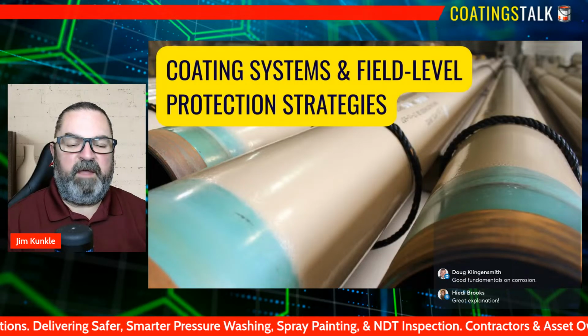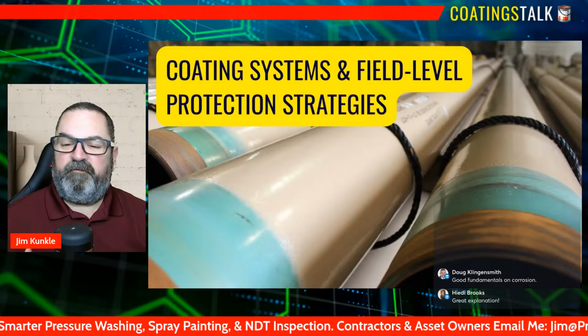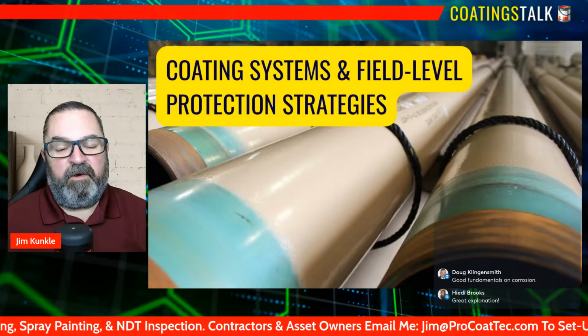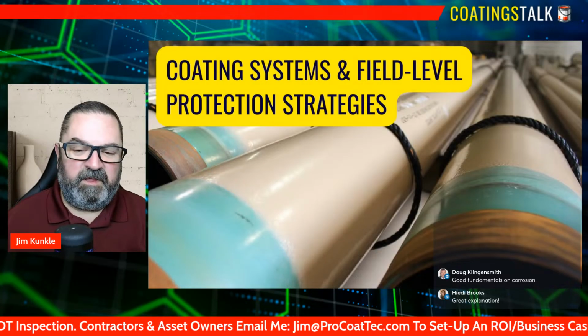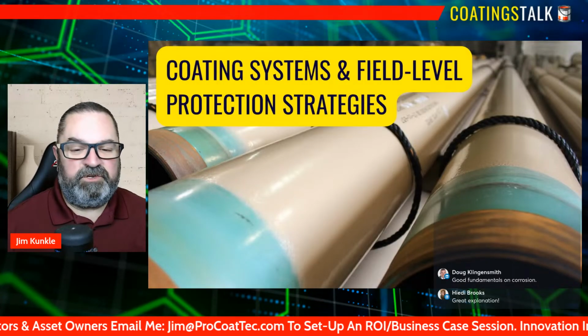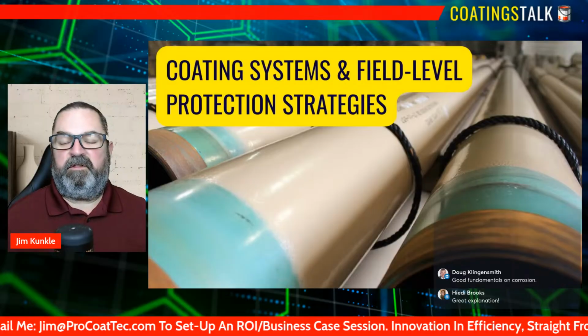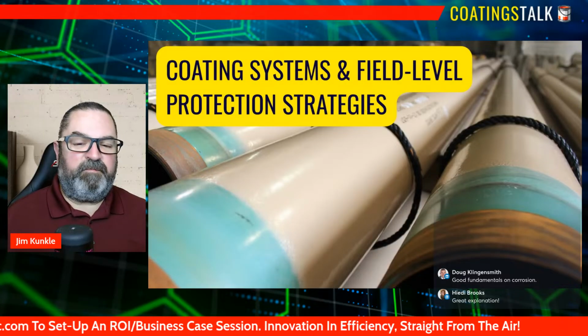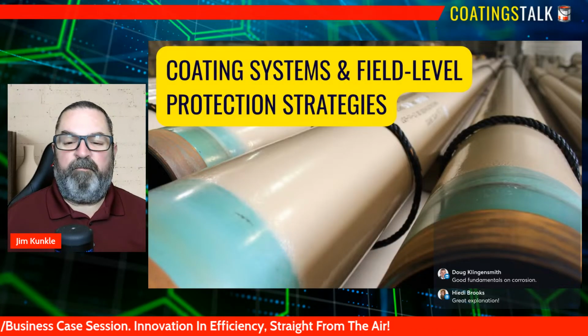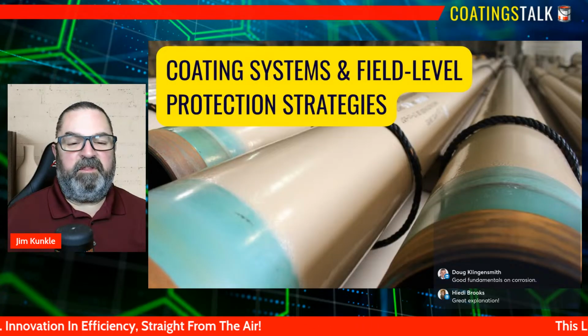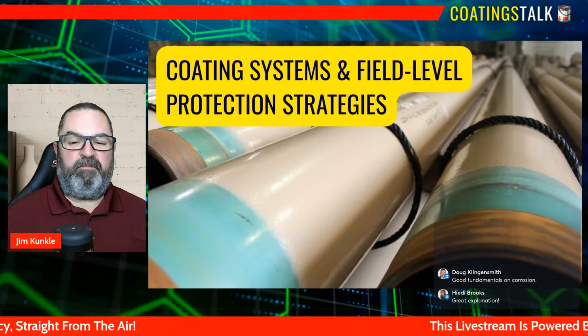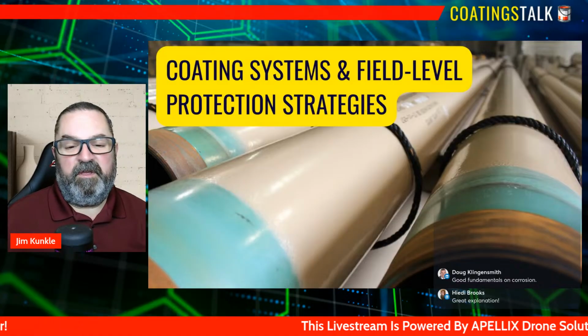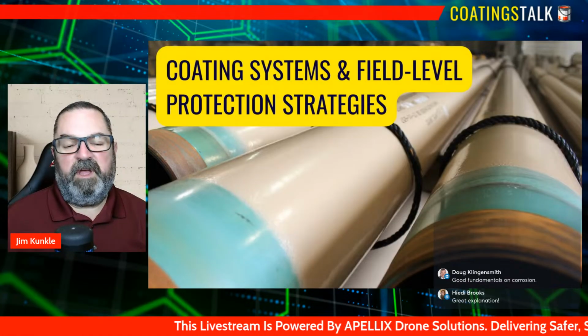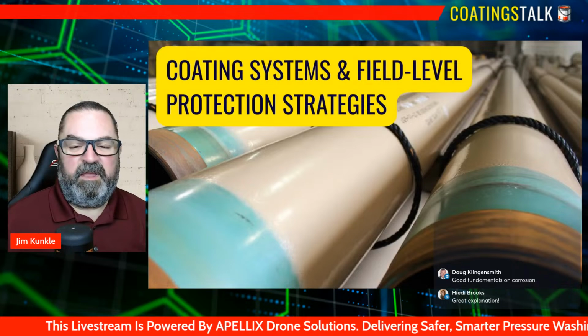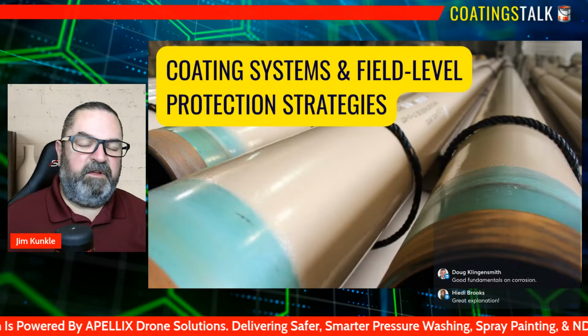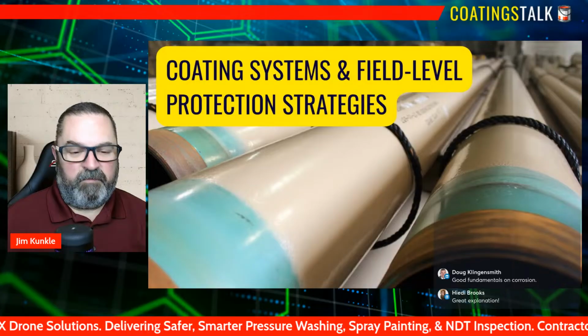Coatings need proper time and the right environmental conditions to fully cross-link and develop their intended chemical and mechanical properties. If a coating is exposed to moisture, low temperatures, or even service conditions before it's cured, its protective network may never fully form. And this results in soft films, poor adhesion, and reduced resistance to chemicals or abrasion. Field teams who respect cure schedules and monitor temperature, humidity, and the dew point give the coating the chance to reach its full potential in performance.